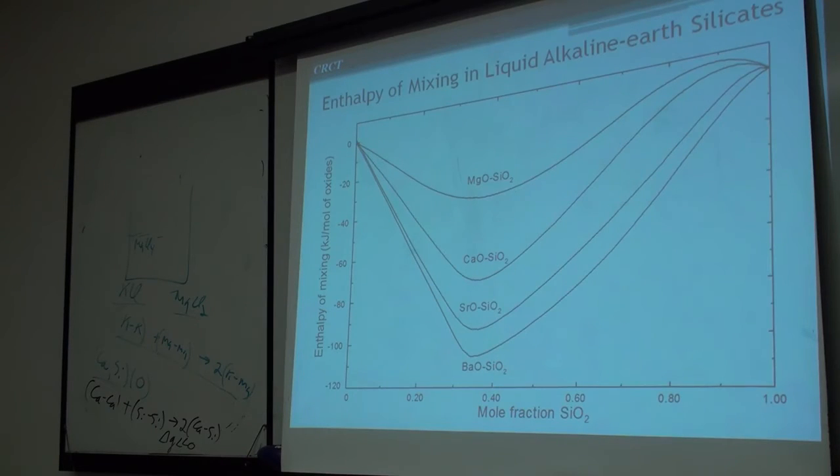This is the same trend now as we saw in the salts I showed you with alkali chloride, magnesium chloride. If you went down lithium, sodium, potassium, rubidium, cesium, you got further and further down. This is the same thing. Now you're going down the alkaline earth series. The magnesium is a smaller ion, so you get to the bigger ions down here. The barium tends to give you a stronger tendency to the complexing.